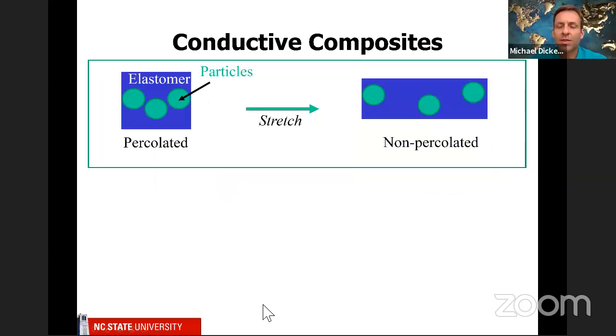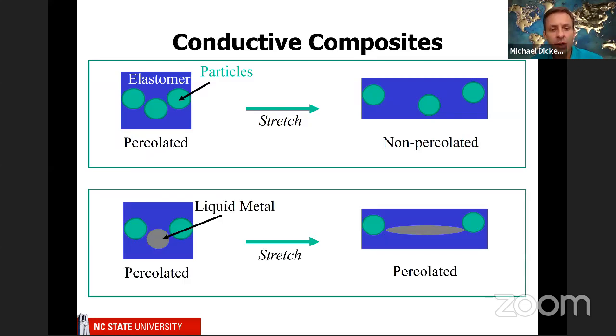And the reason for that is kind of easy to intuit. That is, if you have a percolated network of particles through which charge can flow, if you stretch them, you move them farther apart. Very simple to understand. You just increase the resistance because it's more difficult for charge to pass through the particles. But if you add liquid metal particles, when you stretch the composite or deform it, you actually deform the liquid metal and thereby potentially could be changing the conductivity. And in fact, that is the case.